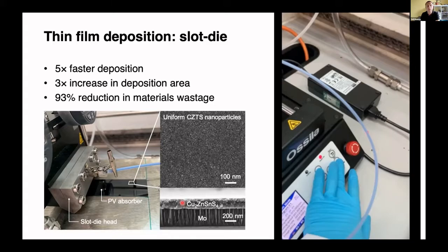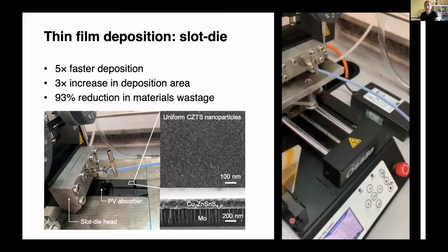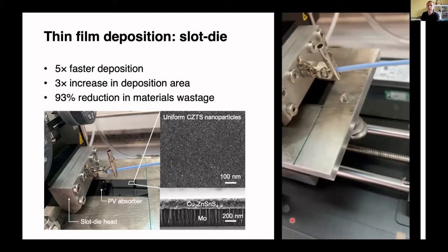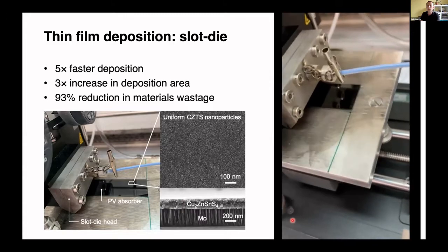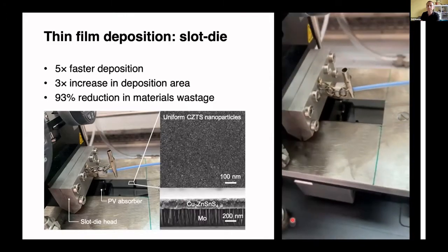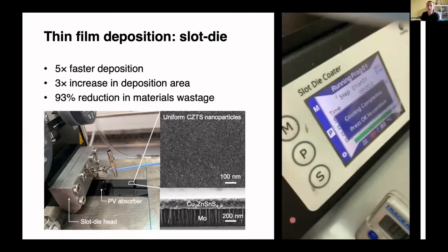And then in cross section, it looks nice too. And we can make this much more quickly and with much less wastage than with the spin coating technique. So that's great from a sustainability point of view, but also, we're able to make larger samples, which is nice. So here's a video of the thing happening in action. Here you can see the slot die head being dragged over the substrate, and you get this really nice uniform absorber.